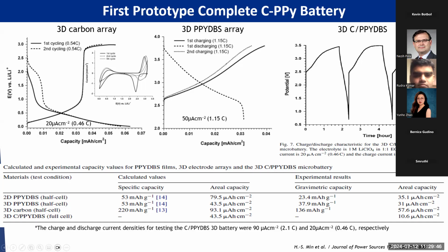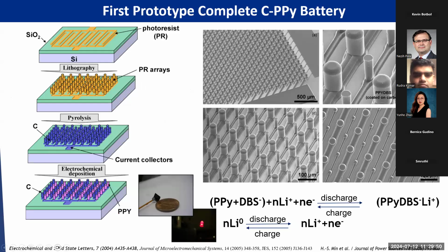What's the reason? If you look at this structure, you can see the majority of the space will be just electrolyte. You can't really make this 3D battery very close. Once you want to make it very dense, there's 2 issues. The anode and the cathode can touch each other, then you short the whole device. And we try to keep the volume as much as we can, all the active materials, but still the majority space will be just electrolyte. So we don't have enough active materials in this case. And secondly, carbon is not the best electrode current collector because there's a resistance for carbon, especially when you scale up, make a high aspect ratio electrode.